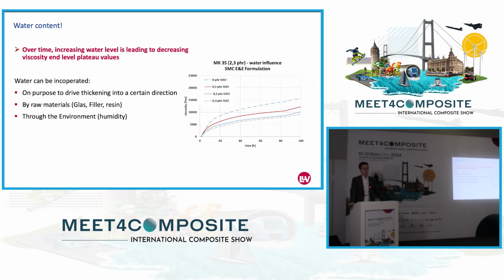Another topic is water. Currently, we often get the request, because people try to make their SMC a little bit lighter, that the thickening performance is off, and we should investigate what happens. At the end, we found out that some of the people change their solid additives, like for example the zinc stearate, with a liquid one, which contains a lot of water.